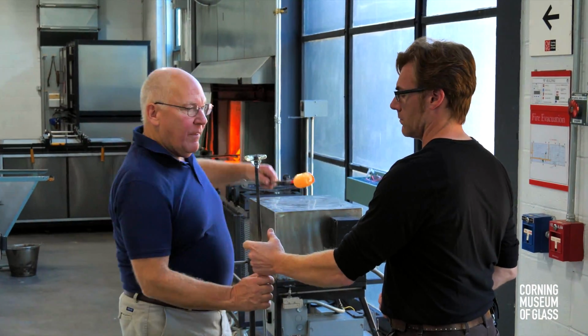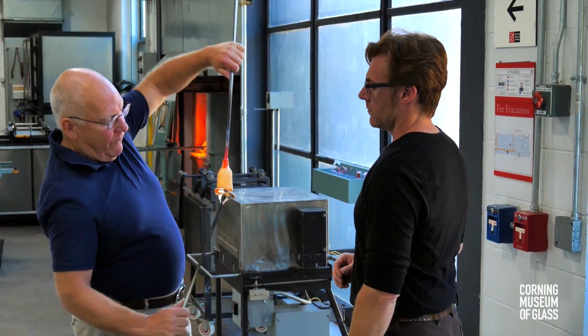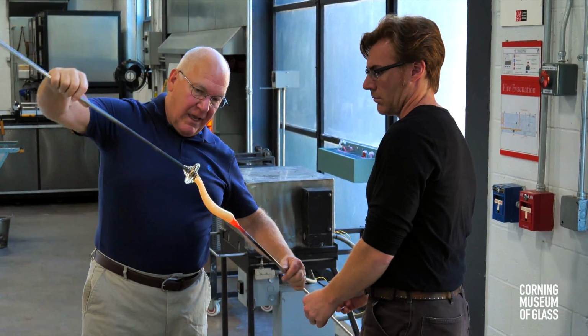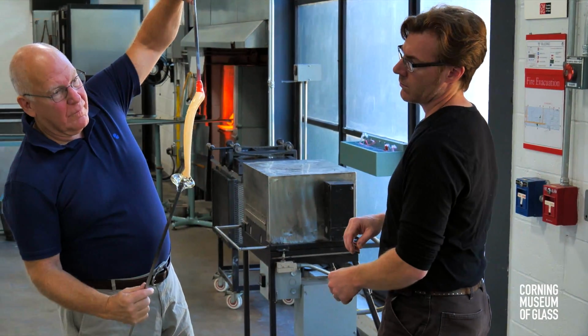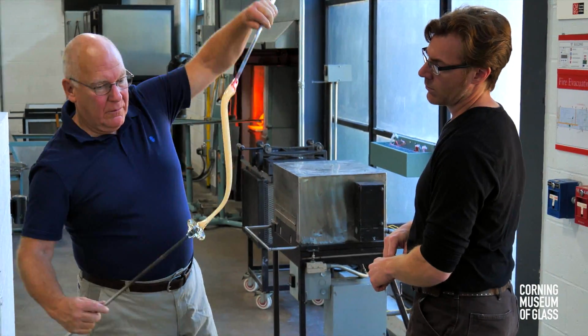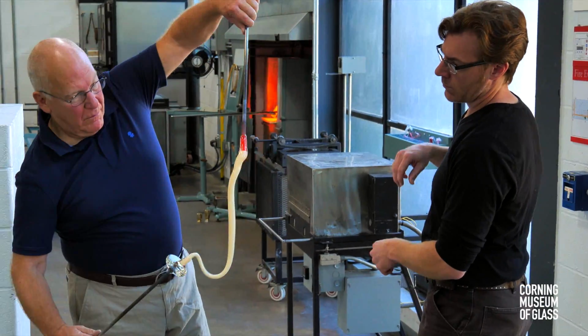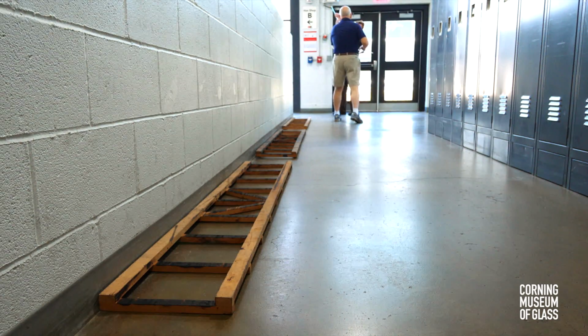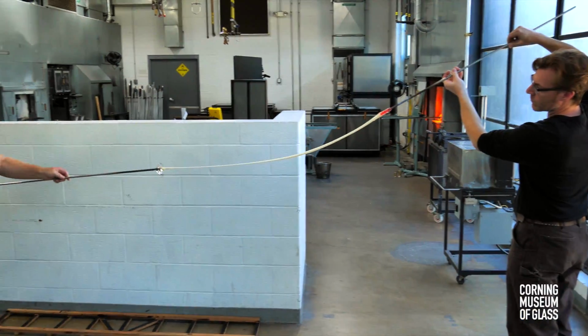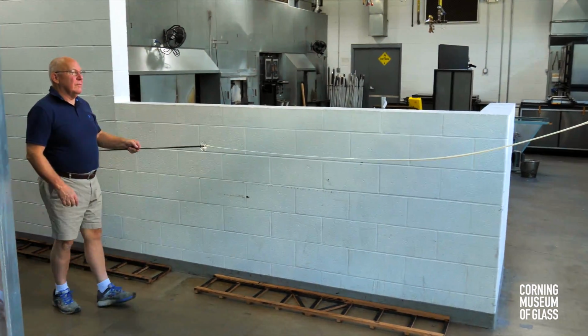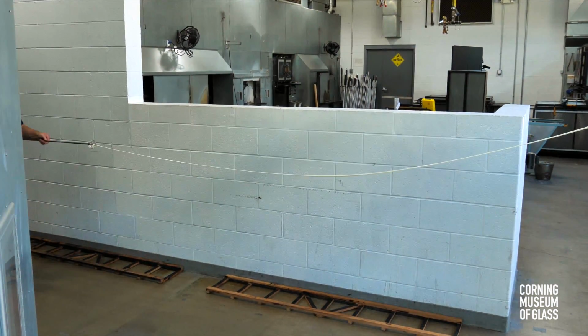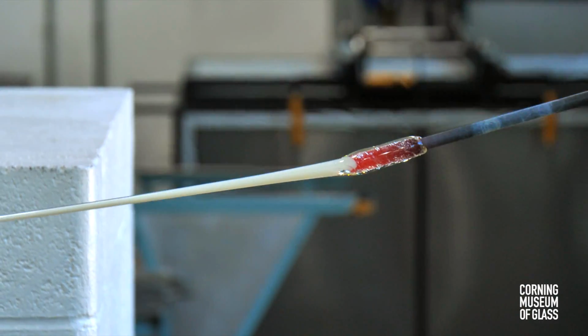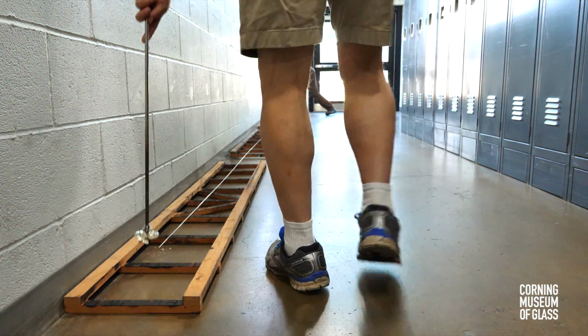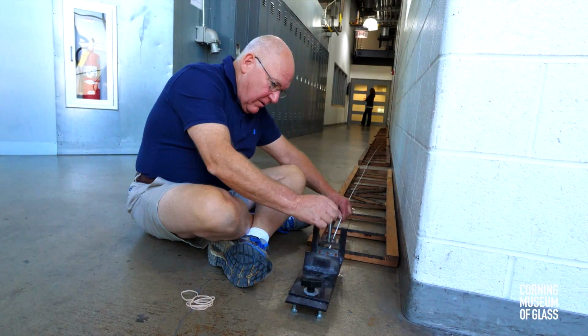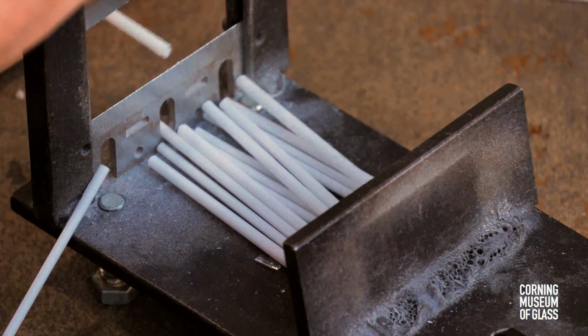The cane is pulled by attaching the white glass cane to another post of glass on the end of a different metal rod. The glass is gradually elongated and pulled to a cane of about a 20-foot length. After the cane cools, it's cut into lengths of about 4 inches.